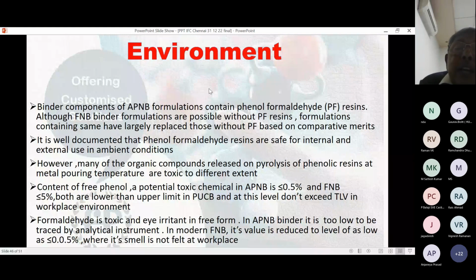However, many of the organic compounds released on pyrolysis of phenolic resins at metal pouring temperature are toxic to different extents. Content of free phenol, a potentially toxic chemical, is less than 0.5% in Alphaset and less than 5% in Furan. Both are lower than the upper limit of the most widely used core making binder, phenolic urethane cold box. But I won't say that this is not harmful. It has to be reduced further.